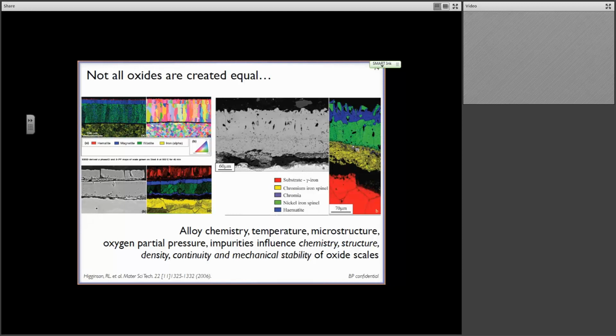This is just another example here. Chromium, even in good stainless steels, still forms multiple layers of oxides, not all of which are passivating, and not all of which are necessarily mechanically robust. So the way in which we find and create alloys that have good oxidation and corrosion resistance involves a complex combination of changing the alloy chemistry, the temperature at which it will be exposed or used, the original microstructure, the oxygen partial pressure we're exposing it to, and impurities, both in the metal itself as well as the environment. All of these will influence the chemistry, structure, density, continuity, and mechanical stability of the oxide scale, and that's what's critical for actually improving the passivation, preventing corrosion, fouling, or other sort of degradation mechanisms in these extreme environments.